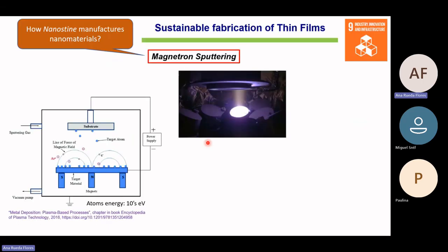So now, let's move to the second part, which is how Nanostine fabricates the material. So we are using sputtering. Sputtering is a physical vapor deposition technique in which, with the help of a plasma in a vacuum chamber, we can remove atoms from a bulk material, the target. We create a plasma from an inert gas, then we accelerate the ions towards the bulk, and by transferring energy, atoms are ejected, and the atoms can be deposited onto the substrate. In this configuration, in which the target and the substrate are parallel, or as you can see in this picture, quasi-parallel, this was taken, by the way, in an AJA sputtering, similar to the one that you have here at your institute. What you obtain is a thin film.